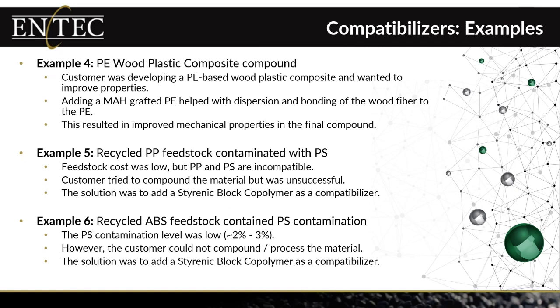So the styrene end groups are compatible with the polystyrene component, and the olefinic mid block in these materials is compatible with the polypropylene. Once again, they make very, very good compatibilizers for these types of mixed feed streams. I had another customer that used recycled ABS, and they would get occasionally some polystyrene contamination. And while polystyrene has some compatibility in ABS, it's not that great.